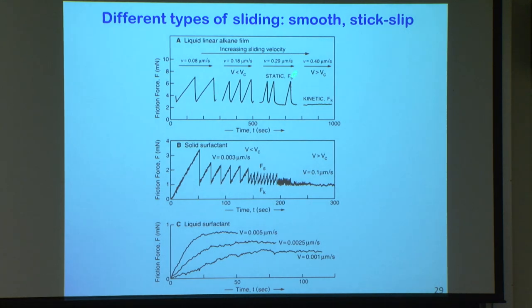You can have very regular stick slip, and then above a certain velocity, it will disappear altogether. Or you can have stick slip where, with increasing velocity, the amplitude goes down and the frequency goes up. Or you can have no stick slip at all, where the liquid lubricant behaves like a viscous one, and then with time, as you reach the maximum, it starts moving and it moves at a higher force. And this is just explained by Couette flow or Poiseuille flow.